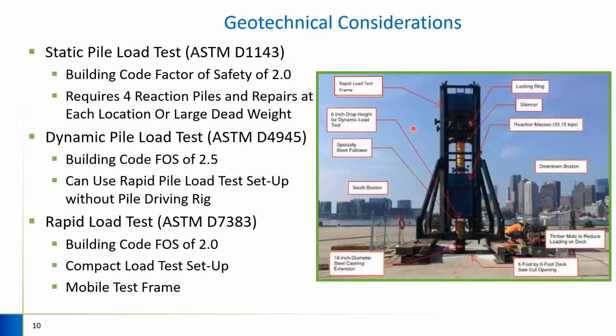And so for this reason, and due to the concern that we may have some issues with some of the piles themselves due to their age, we determined that we wanted to use both dynamic pile load testing in combination with rapid load testing in order to reuse the piles without significant issues should loads be close to the design loads. And therefore, we ended up deciding that we would use rapid load testing.